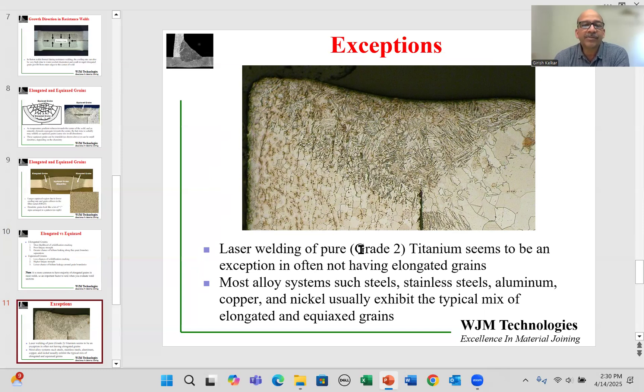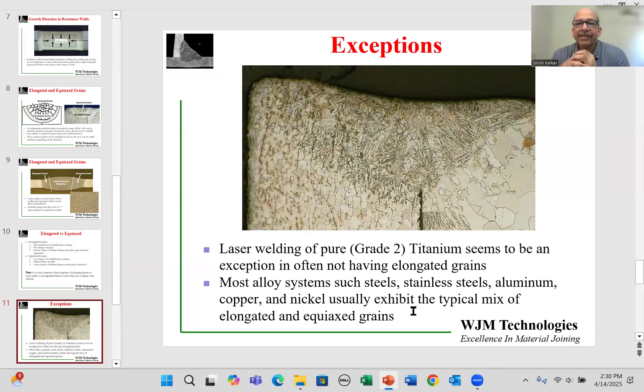There's always an exception to the rule. This is a laser weld in titanium, a very small weld typical for medical devices. You can see that you do not have very obvious elongated grains along the boundary, and this is something I've typically seen in grade two titanium. I'm not sure why that happens in titanium and not in other alloys. But most alloy systems — such as steel, stainless steel, aluminum, copper, and nickel alloys — will typically exhibit a mixture of elongated and equiaxed grains depending on the metallurgy, size, shape, cooling rate, and so on.